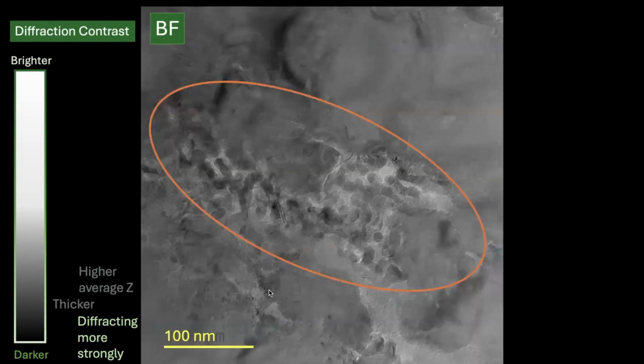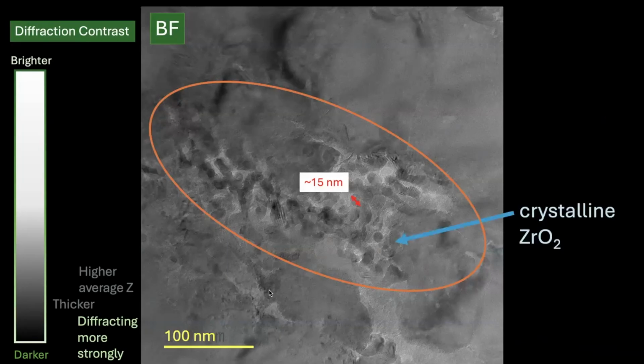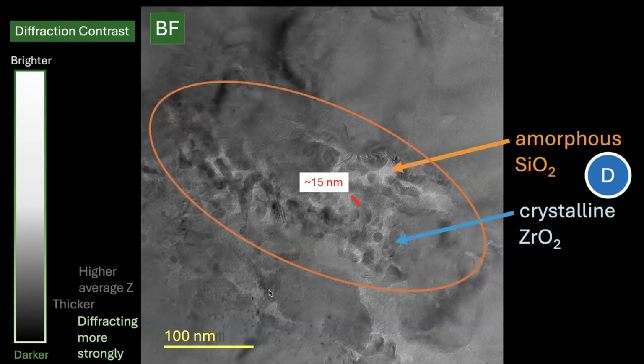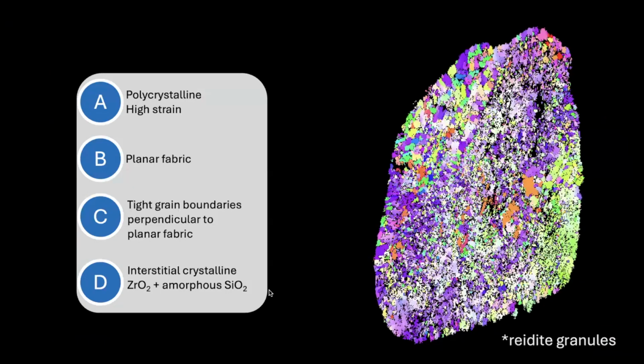And then really diving into those fine grained regions. These are about 15 nanometer crystallites. And we have crystalline zirconia and amorphous silica. So this is our fourth piece of evidence. So we've got polycrystalline, high strain, a planar fabric, tight grain boundaries perpendicular to that planar fabric, and interstitial crystalline zirconia and amorphous silica. All of this is pretty consistent with the FRIGN origin, especially since we do have the Reidite granules in here.